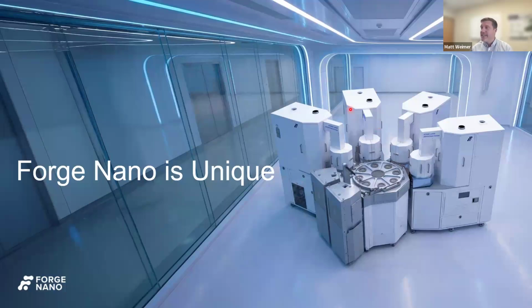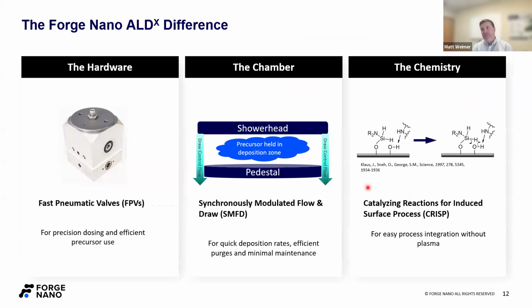Here's a nice, we'll say, generated image of our recent high volume manufacturing tool we call Tefra. It's built on technology that has three key differentiators. The first is the hardware. We call these fast pneumatic valves. This is how we introduce the precursor. Those work in tandem with the reactor design, which we call synchronously modulated flow and draw. It's a mouthful. You can call it SMFD if you like. And then we prefer to use surface chemistry over plasma to improve our film properties.